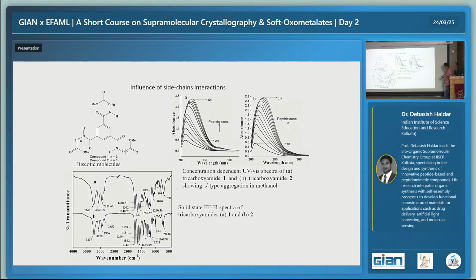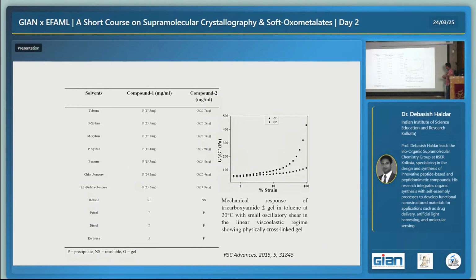And then again, this is something we have played with, the discotic tricarboxyamide, and now instead of aromatic compounds, we have placed aliphatic ones. So now we placed beta amino acid and gamma amino butyric acid with this benzene tricarboxylic acid, and again we see from UV-visible spectra that it's following a J-type of aggregation. But when we studied the gelation property, we see that when it is beta amino acid, it forms a precipitate out of solution, and when it's gamma amino acid, it forms a gel in the solution. So everything is the same, there is only one change of a CH2 group, and we are getting two different material properties from this compound.